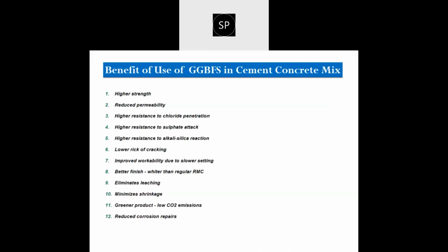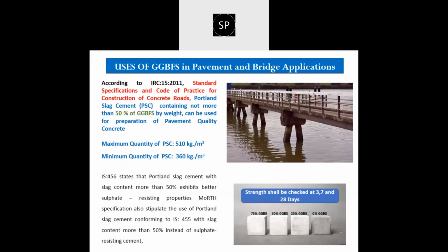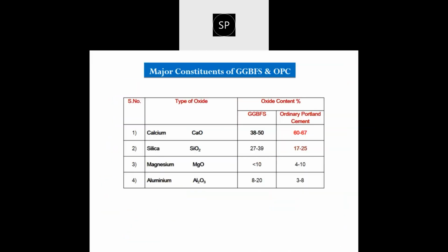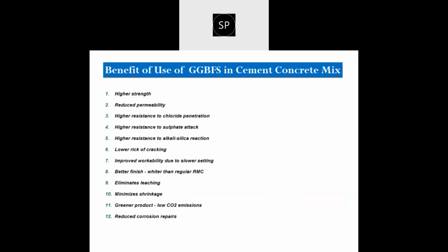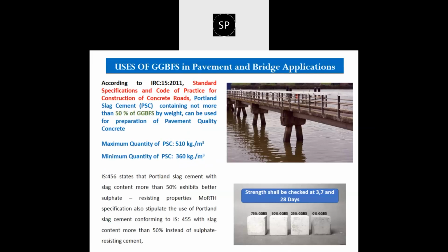So it offers improved workability, and besides that, the chances of shrinkage get minimized since this GGBFS contains high silica content in comparison to the conventional OPC. So the silica alkali reaction reduces the chances of shrinkage. It is a green product since by utilizing the GGBFS, we are facilitating waste utilization in a productive manner. Therefore it offers a carbon credit, and since there is no clinker manufacturing process involved as in the construction of conventional OPC or PPC cement, this sort of material has low CO2 emission. It reduces the corrosion potential, and therefore the steel bars or reinforcement placed inside the structure will have longer durability in comparison to conventional OPC and PSC cement.